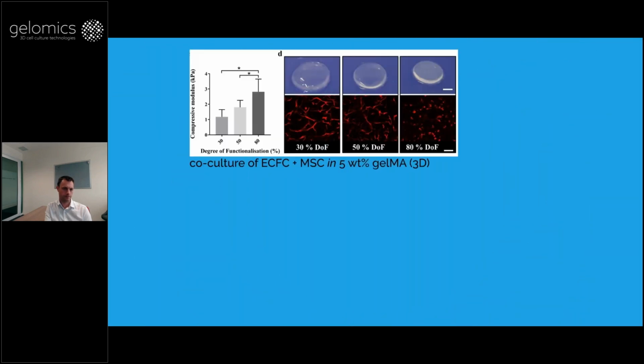In terms of vasculature, blood vessels, we've looked at the capillary formation within Gelma, and saw we really needed really low stiffness, below 2 kilopascals. We saw the capillaries forming. As soon as you get to 3 kilopascals, you get 80% DOF. The capillaries no longer formed inside the gel, so really soft gels.